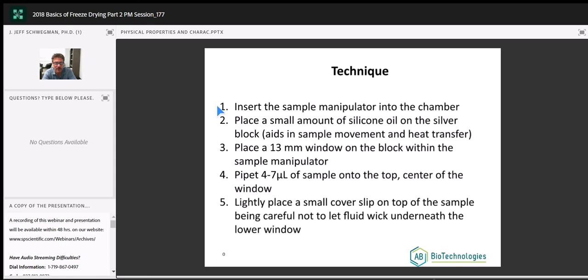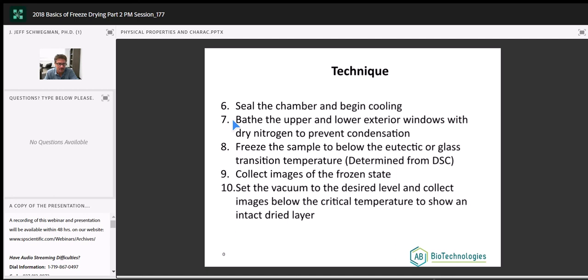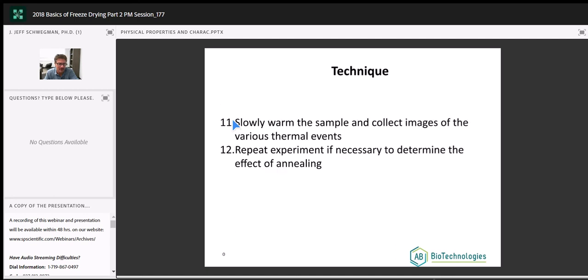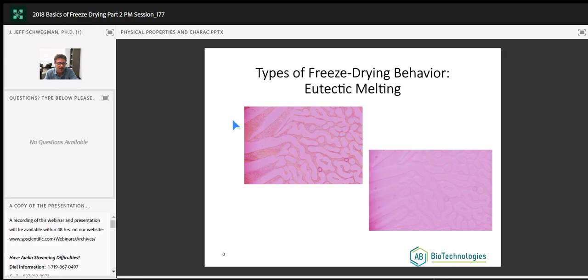I'm not going to go through the technique. This is, again, something that we do in our lab. If you do have this technique available in your facility, this is the technique that we use. It's relatively simple. We put the windows down. We do use a small amount of silicone oil between the sample block and the quartz bottom window. That helps with heat transfer and also provides lubricity because we can actually move that sample around under the microscope while it's freeze-drying. Again, different techniques, some of the technique here.